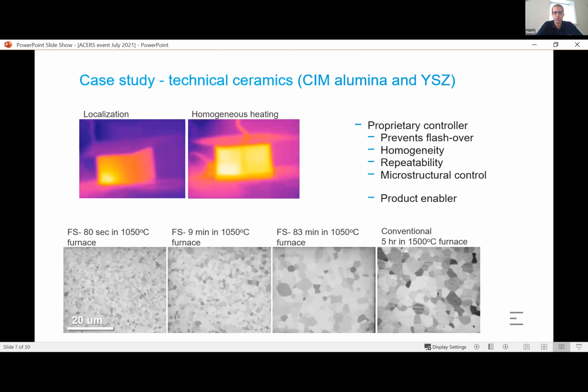But then as we start to optimize and really look at different flash settings, what we can start to see is conventional sintered microstructure here, and this is uniform. All of these images represent a cylinder of zirconia that is the same density that's achieved in conventional. We've got five hours at 1500 degrees here on the right hand side on the micrograph.